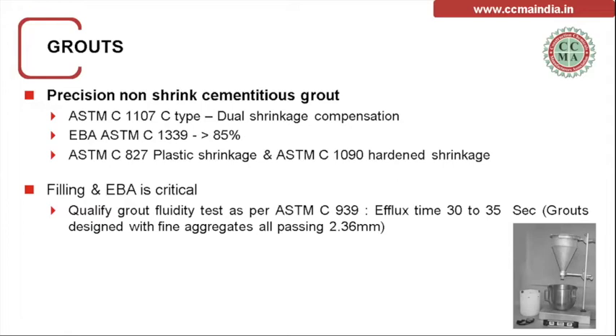Then plastic and hardened shrinkage will be measured as per ASTM C827. The important thing here is that the plastic shrinkage compensation expansion should not go beyond 1%. That is how a good grout should be designed. So I will come to the most critical part, which nowadays we don't see much in the specifications from specifiers, other than compressive strength, flow, and 1-day and 3-day strength. I would rather give the most importance, for the grout to be successful in achieving the intended usage, to the flowing ability, the fluidity of the grout.